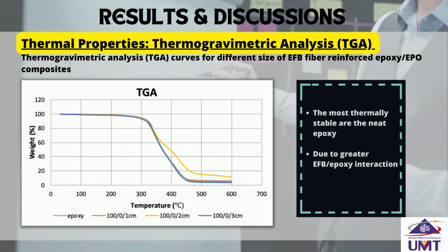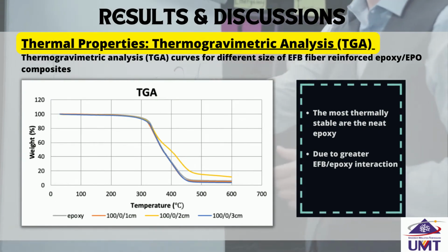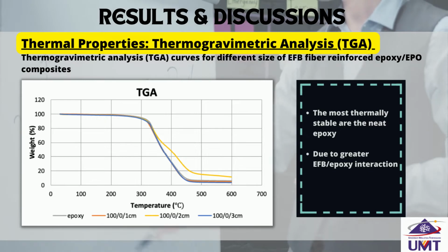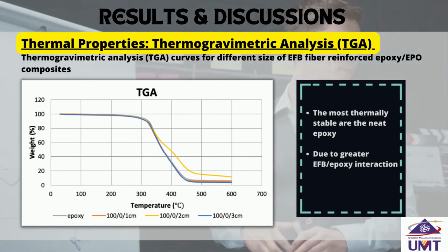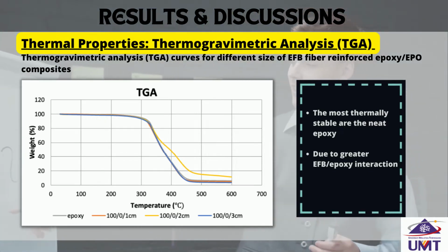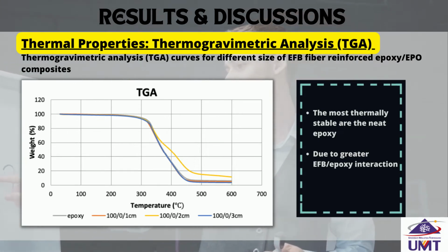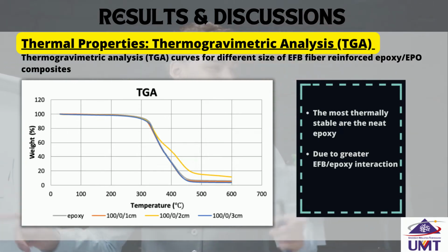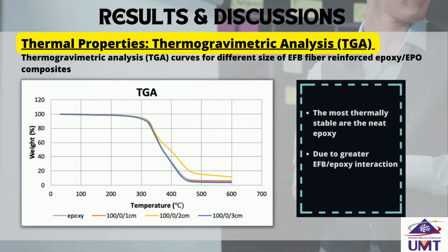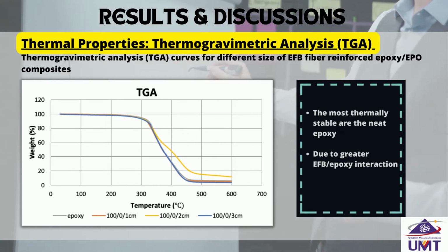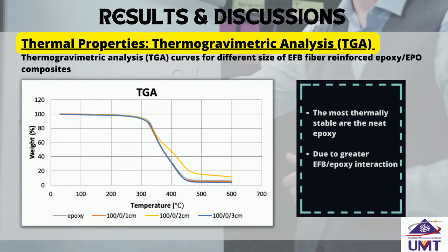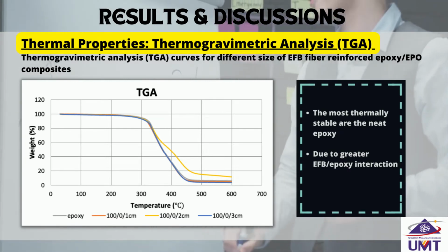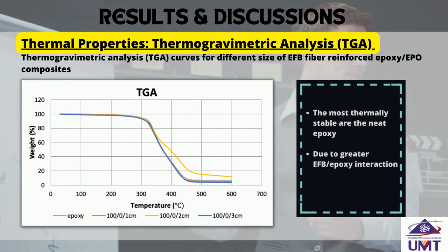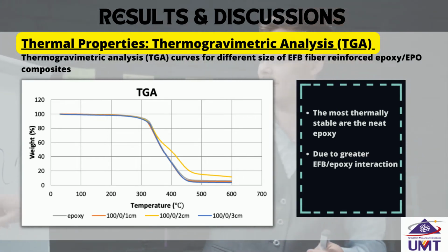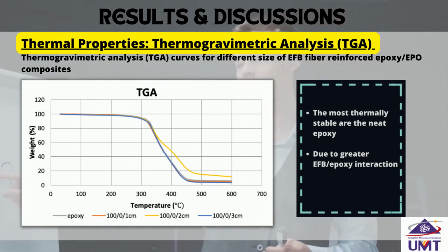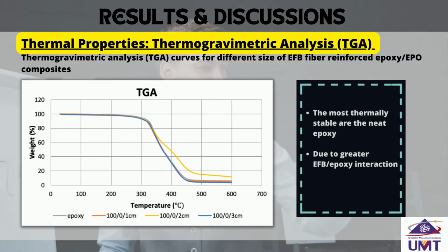Results and discussions for thermal properties, thermogravimetric analysis, TGA. TGA result shows a curve of weight loss variation with temperature. Based on the data, the results for all samples are slightly similar to each other. From the observation on the graph, mass loss slightly under 200 degrees could be attributed to absorbed moisture evaporation. Even though the fiber was dried in an oven before running the TGA analysis, the moisture begins to evaporate at a temperature of 80 degrees because it is difficult to eliminate water.